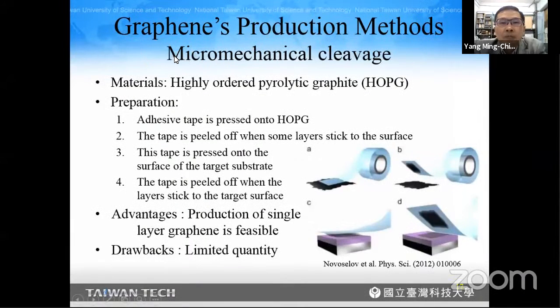And the first method is micro-mechanical cleavage. The material is highly ordered pyrolytic graphite. First, we use adhesive tape, such as scotch tape, placed onto this HOPG. The tape is peeled off when some layers stick to the surface. And this tape is placed onto the surface of the target substrate, for example, a silicon wafer. And the tape is peeled off when the layers stick to the target surface. The advantage of this method is that production of single layer graphene is feasible. And the drawback is that the quantity of graphene is limited.